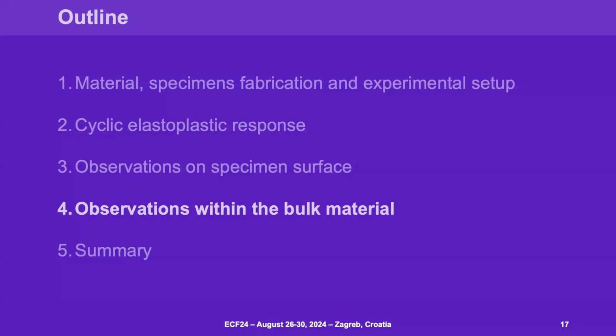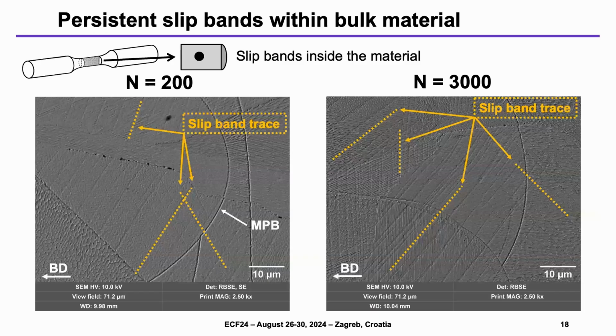Okay, so these persistent slip marks that were observed on the surface of the material, as I said at the beginning, are related to the bands within the bulk material, so in the interior of the material. So at this point, we decided to investigate also the interior of the material, in this case of the cylindrical specimen. So we extracted some samples and we performed EBSD analysis.